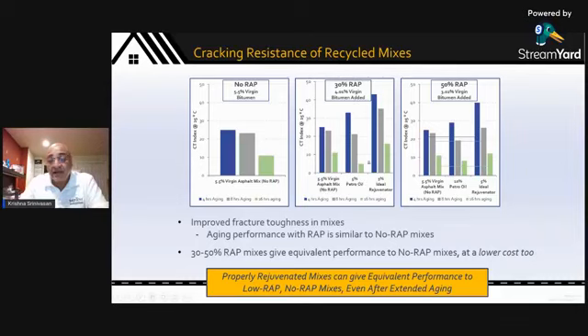And in another case, we studied 3% of our rejuvenator, and we looked at the same 4-hour, 8-hour, and 16-hour aging. And what you can see in the case of the petro oils is the instantaneous value is high, but after long-term aging, the performance falls off drastically. And this is true in both 30% and 50% RAP mixes. And you can see that with our rejuvenator, you're able to maintain or better the aged performance of the roadway. And that is a key highlight that I want to re-emphasize to you.